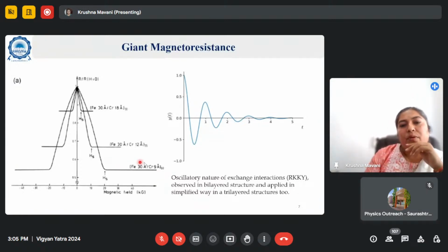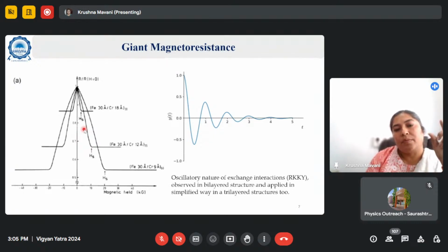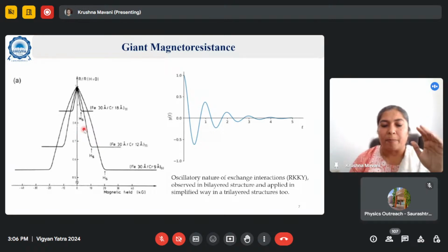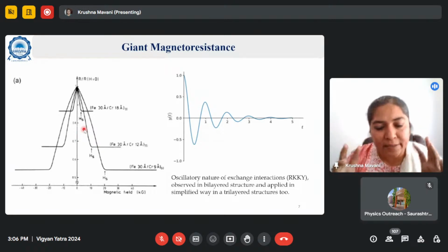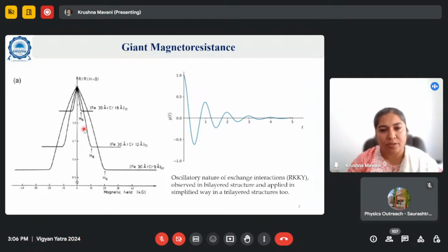Now, these kinds of results, when thickness is changing, the magneto-resistance is changing because of the thickness. There is a thickness dependence. That is because of the RKKY type exchange interactions. These are not normal, nearest neighbor direct exchange. It is called indirect exchange interactions, and they depend on the distance between the two charge carriers carrying the spin.